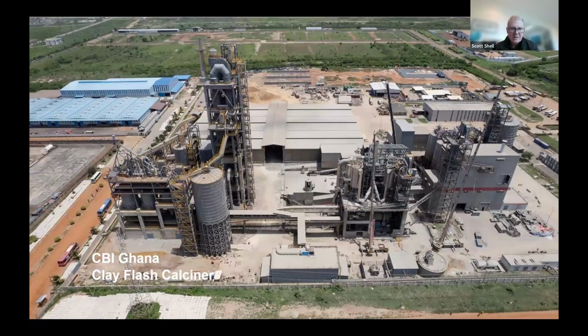The other primary way to calcine clay is in a flash calciner. This is the tower that you see on the left. It's very, very similar to the pre-calciner tower that we saw in cement production. It's a tall tower with a bunch of cyclones in it. It circulates that powder, suspends it to transfer the heat to it to create that chemical activation, that chemical conversion. Although in this case, there's no CO2 in the clay, so you don't have those process emissions, just the energy emissions. So this is the flash calciner. Those are the two primary ways.